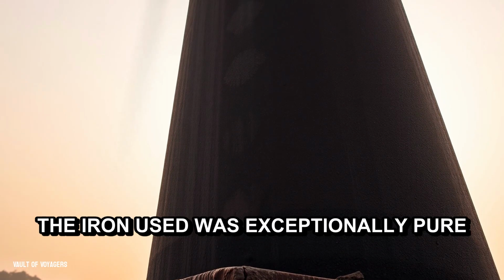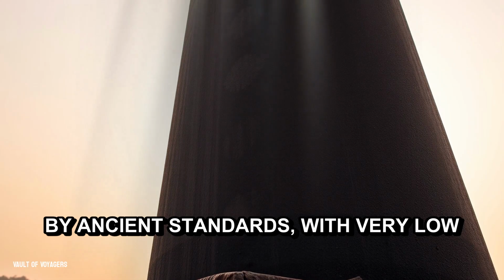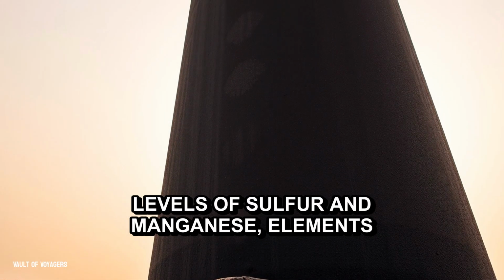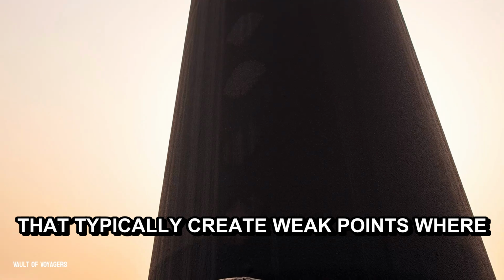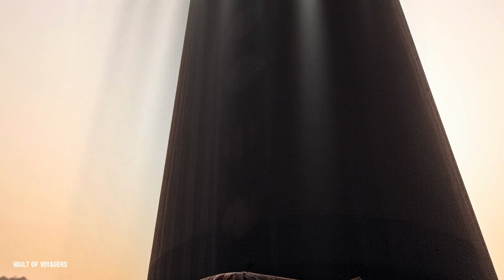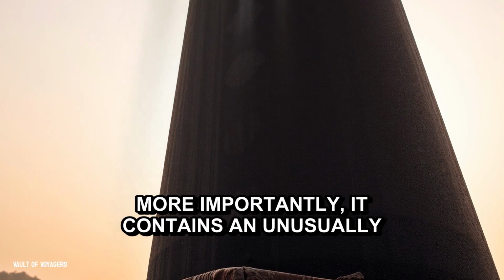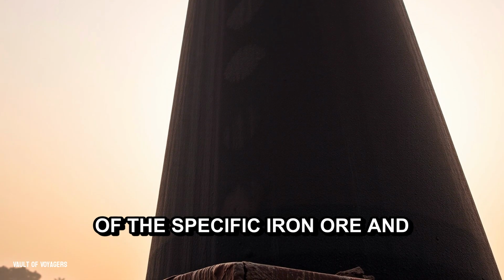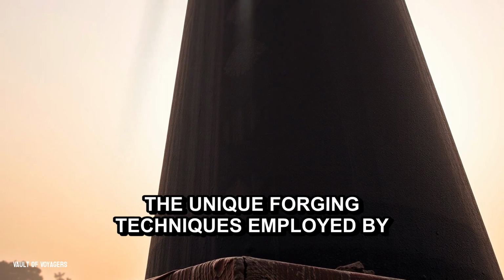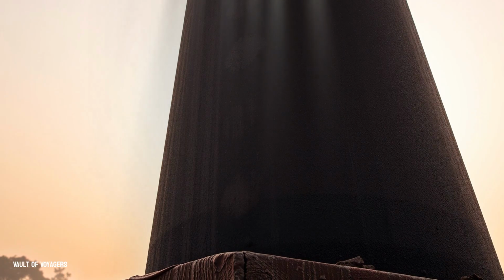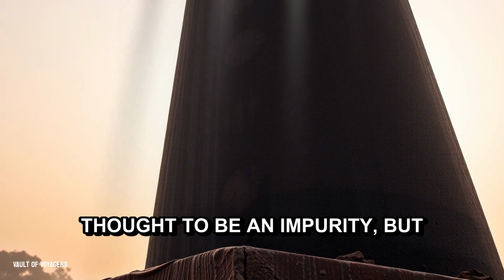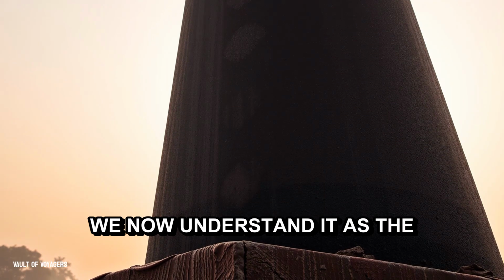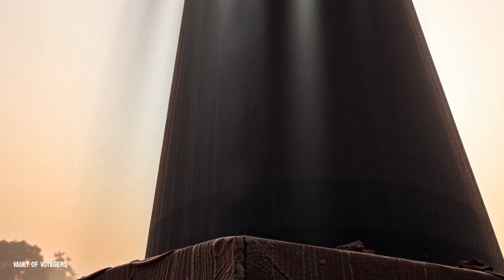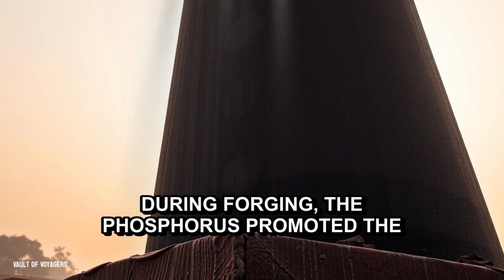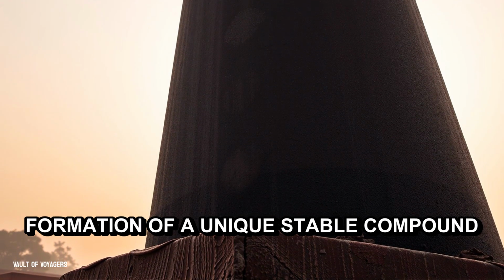The iron used was exceptionally pure by ancient standards, with very low levels of sulfur and manganese, elements that typically create weak points where corrosion can begin. More importantly, it contains an unusually high amount of phosphorus, a result of the specific iron ore and the unique forging techniques employed by the Gupta period metalworkers. This high phosphorus content was once thought to be an impurity, but we now understand it as the cornerstone of the pillar's immortality. During forging, the phosphorus promoted the formation of a unique, stable compound within the metal's microstructure,